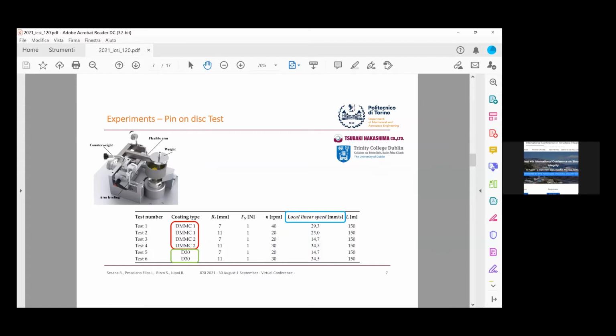As a result of preliminary work, it was concluded that for each combination of bearing ball, that is the pin, and coated substrate, the plate, two wear measurements were performed by imposing the pin-plate contact at 7 and 11 millimeters from the disc center, and by adopting different values of relative rotating speed between 20 and 40 RPM. Normal load and sliding distance were fixed at 1 Newton and 150 meters respectively. Testing conditions adopted for the performed tests are synthesized in the table, and as you can see, what differs from each test is the local linear speed.